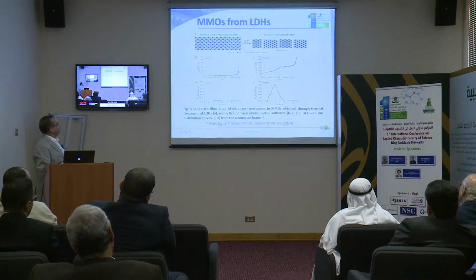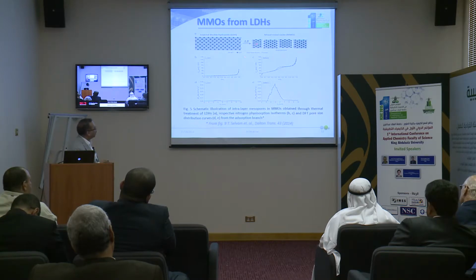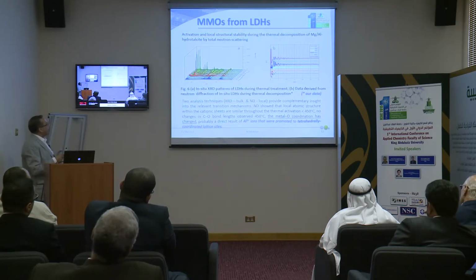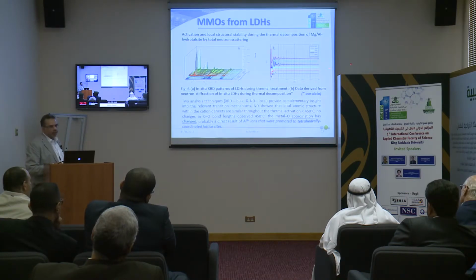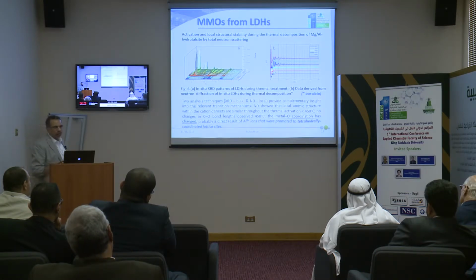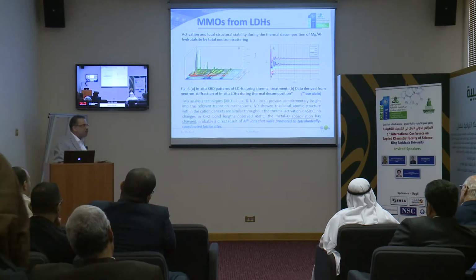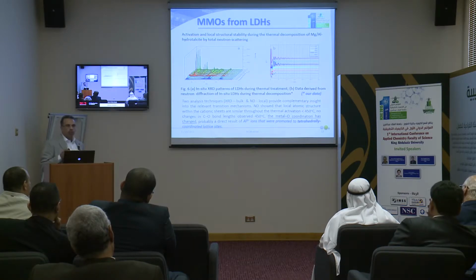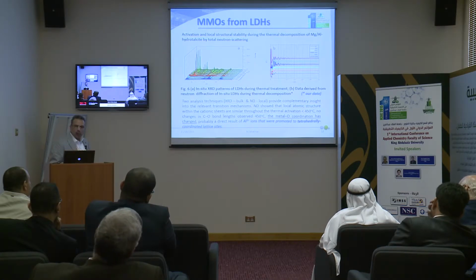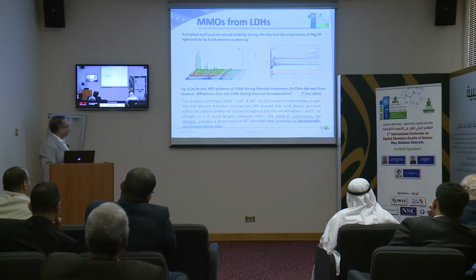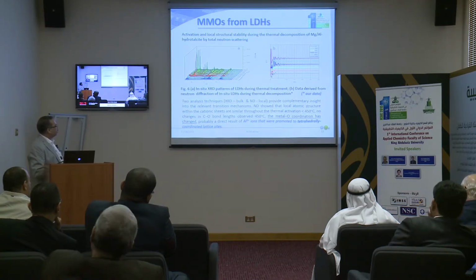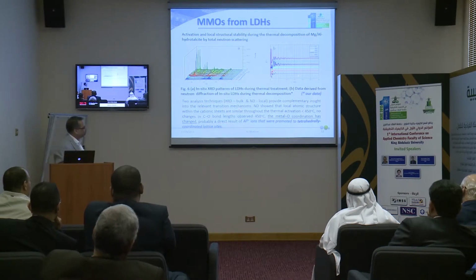Again, by calcination of the as-prepared material, you can create a nice mesoporous material with large surface area. In our previous studies, we tried to find an answer to what's happening during in situ calcination of the material, what's the phase transformation, what could happen, is it possible for the cations to leave the octahedral site in the cationic sheet, or will they stay in the octahedral site, and what's the effect on the catalysis? So we did in situ XRD measurements as well as neutron diffraction measurements.